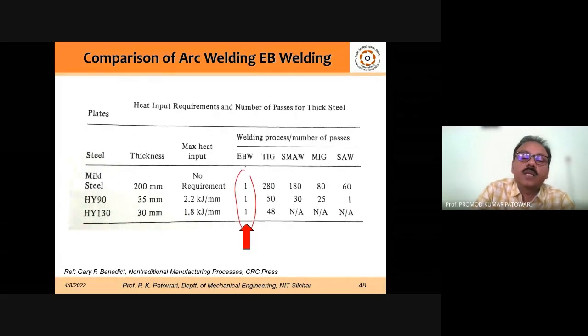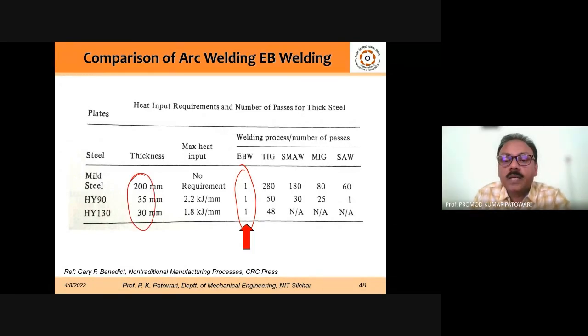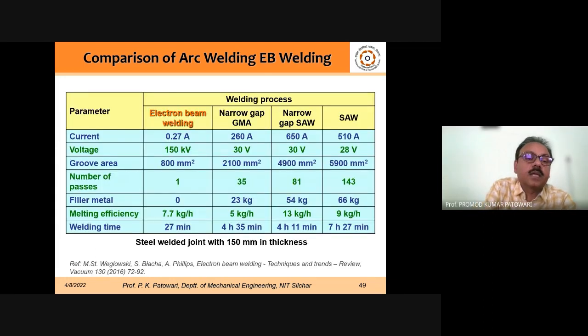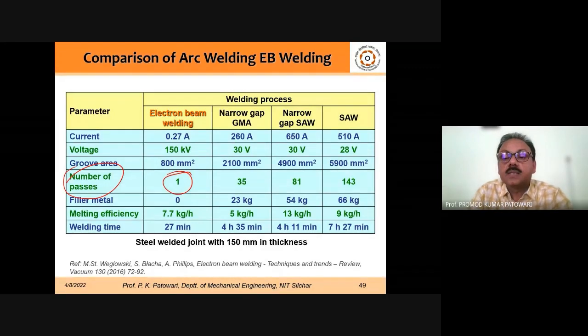One biggest advantage you are getting is that even by a single pass, quite a larger thickness you can weld. Whereas in other processes, 180, 60, 200 number of passes are required, and there only one pass can weld up to say 300 millimeter deep plate in one go. So you can see the number of passes in electron beam. That is the depth it can achieve. There's only one, because of the high density and low area, so it is quite focused. So nice welding you can get, and the heat affected zone will be minimum.